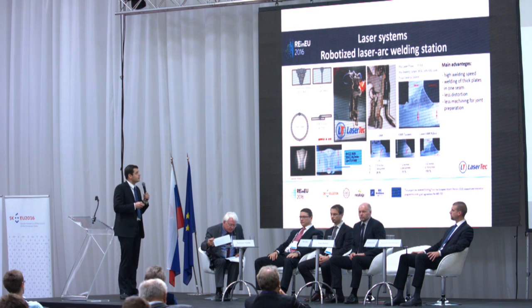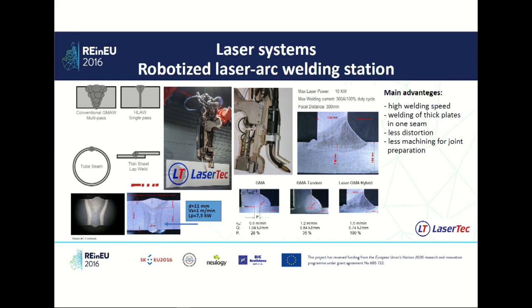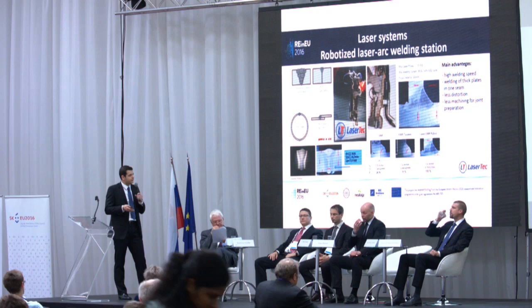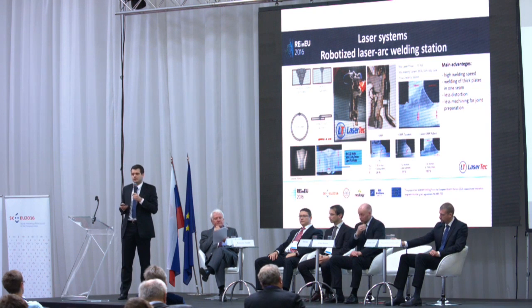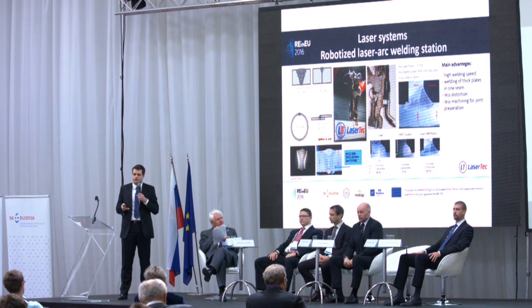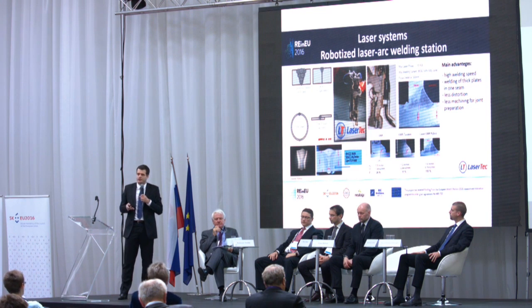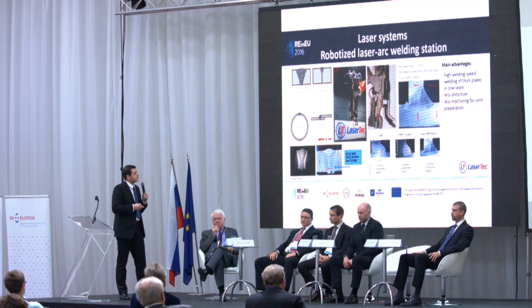Laser arc welding process, so a combination of laser beam welding and the conventional arc welding process. So in one process you have the advantages of both of these technologies. The main advantage is high welding speed. You can achieve 3 up to 4 times higher welding speed in comparison to arc welding. I have even seen applications with welding speeds up to 6, 7, even 8 meters per minute using a tandem torch. Welding of thick plates in one seam.